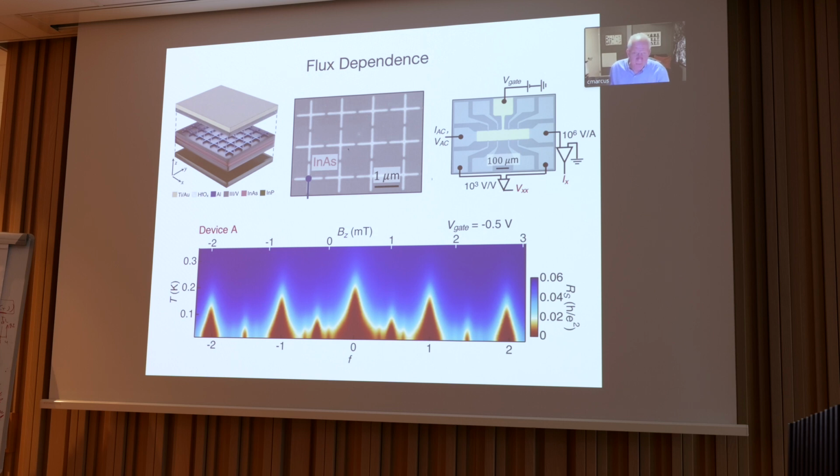You'll notice we've gotten better at etching. This is now a design in which there is a very clear, well-defined area of plaquettes between the Josephson junctions that are formed between the superconductor and the semiconductor. This one has one global gate over the whole system. First, it depletes the puddles, then second, it depletes the junctions, so we can go to a regime of just junctions occupied.